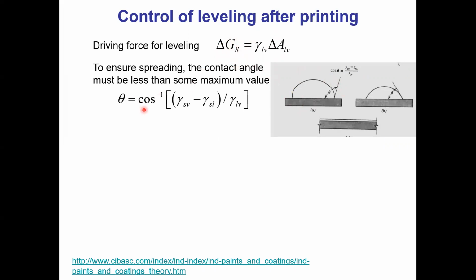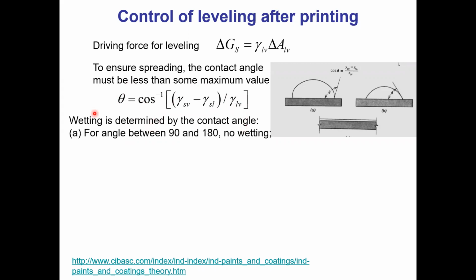In terms of the wetting behavior and the thermodynamics and the rheological behavior of the ink, it's controlled by the so-called contact angle. It's controlled by interfacial energies in the ink, and you can get wetting or non-wetting behavior depending on the contact angle. So if the contact angle is between 90 and 180, it will be non-wetting ink on top of the substrate, not desired. You actually need a wetting type ink where the theta has to be between 0 and 90. You get wetting behavior, but if it's too low, if it's close to 0, you get a spreading and it will bleed out and so on. So you really need the contact angle to be controlled between 0 and 90 degrees.